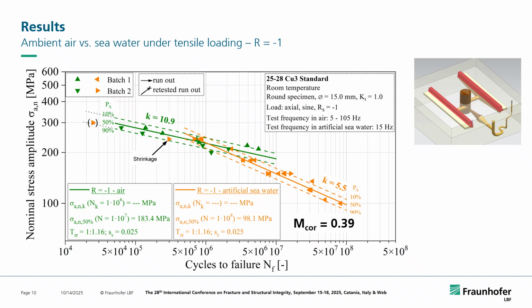The same turned out for alternating loading, the same relationship, around 10, 11 for ambient air in the medium cycle fatigue range, and then something around 5 for the tests under seawater. Here we tested even some longer values, and we get at the end, at the design value of 5 times 10 to the power 8 cycles, around 73 megapascal. And you see here this comparably steep slope, no knee point. And we get roughly at 10 to the power 8 cycles a comparable value for the mean stress sensitivity as for ambient air.